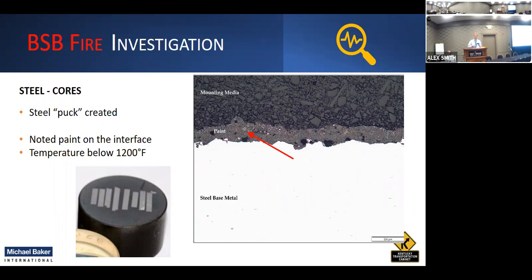So they'd have like 3 micron diamonds in this thing, and they would sit there and rub this thing with a solution that had 3 micron diamonds suspended in it. Then they cleaned it all up, and they finally got down to 1 micron diamond bits, diamond dust essentially in this solution, and grind this thing down to a glass finish and put it underneath the microscope.